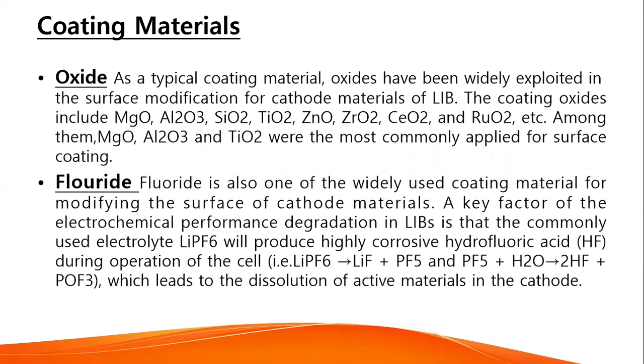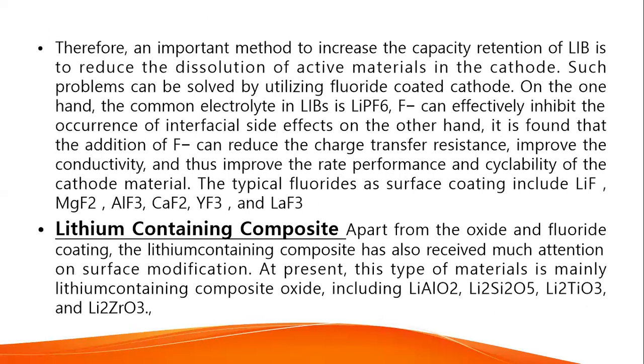Fluoride. Fluoride is also one of the widely used coating materials for modifying the surface of cathode materials. A key factor of the electrochemical performance degradation in LIBs is that the commonly used electrolyte LiPF6 will produce highly corrosive hydrofluoric acid during operation of the cell, which leads to the dissolution of active materials in the cathode. Therefore, an important method to increase the capacity retention of LIB is to reduce the dissolution of active materials in the cathode. Such problems can be solved by utilizing